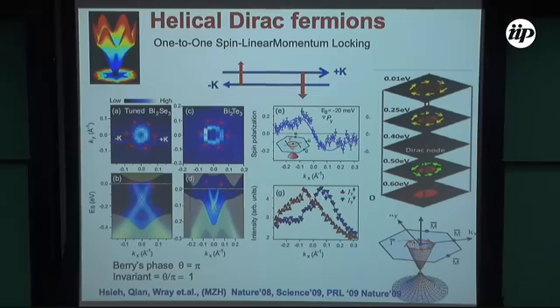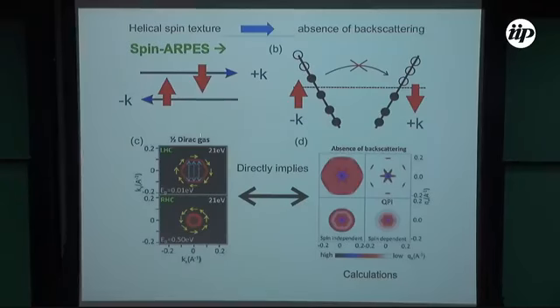And okay, so why is this interesting? If we draw the real space image, the K plus wave packet going to the right is spin down, and this is spin up, and that's all we have on the surface. So now you can see that in a situation like that, you cannot backscatter. This spin texture is not allowing you to backscatter. So this is one way the 2D electronic states on the surface of topological materials are distinct from other types of 2D electron gas systems.